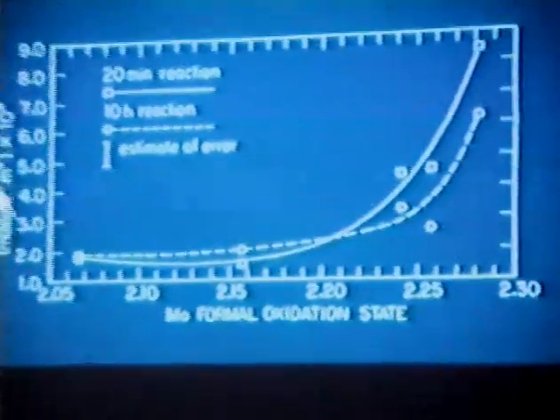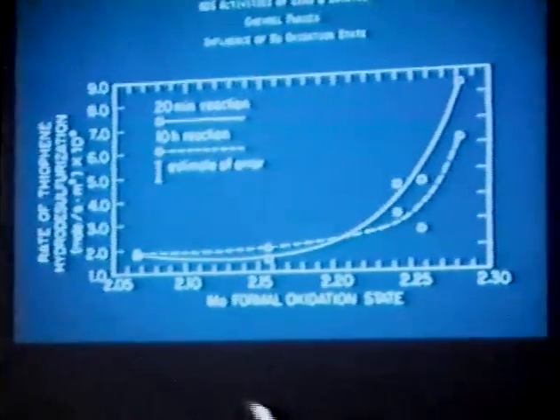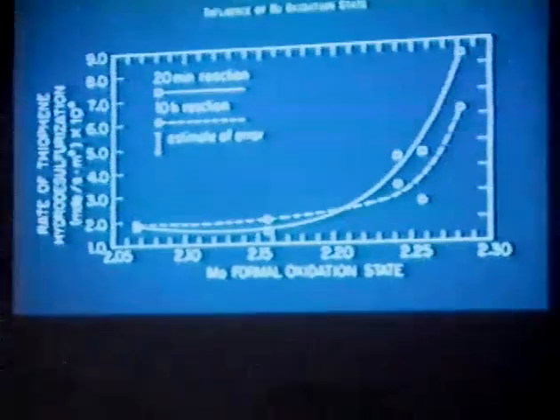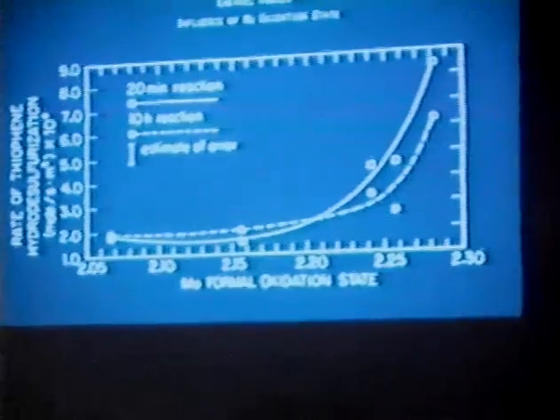Here, using these lead lutetium Chevrel phase compounds, you can calculate the molybdenum formal oxidation state. And here what we've plotted is the rate of thiophene hydrodesulfurization. If you were to put MoS2 on this graph, it would be out here someplace, and its activity would be lower than what's here. So we avoided the temptation of trying to draw a volcano plot here, but it does look like there is some maximum in the catalytic activity.